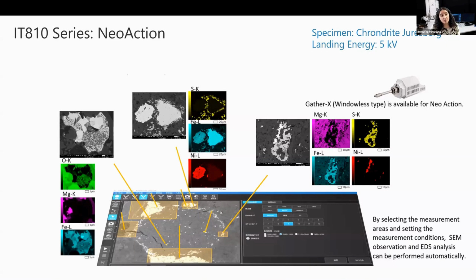So this works very well with the auto functions, even at high magnifications, because a combination of drift correction and beam shift is utilized to counteract the stage reproducibility for fields of view smaller than tens of microns. You can also save and then recall any recipes for routine analyses on different samples. The increased sensitivity of our Gather-X detector enables higher throughput analysis, allowing more comprehensive data sets like this to be collected without sacrificing productivity.